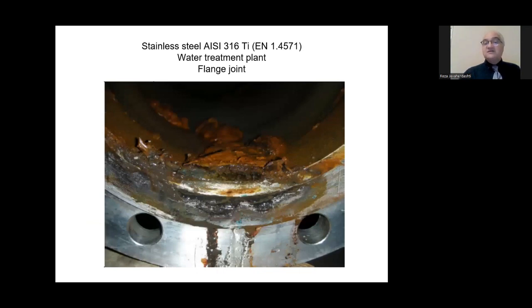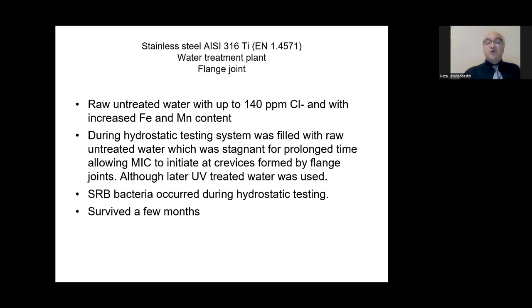Last but not least is this flange joint, where raw untreated water with maximum 140 ppm chloride ion and with increased iron and manganese content was the fluid, and it happened during hydrostatic testing. Although the water had been treated with ultraviolet UV, it didn't work. So this is a warning sign for those operators and professionals who think that by application of UV, the water will be highly safe to be used. SRB bacteria occurred during hydrostatic testing, and this asset survived only a few months.